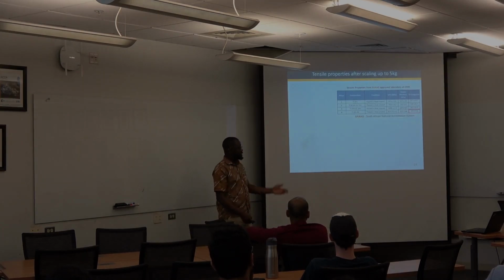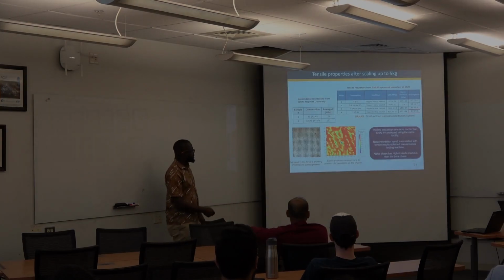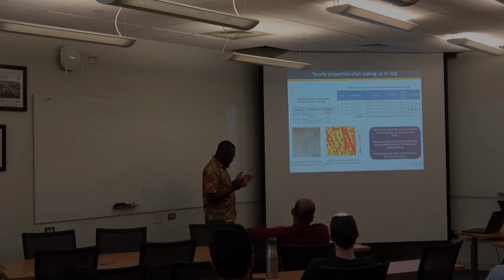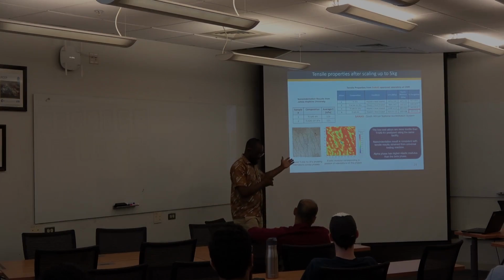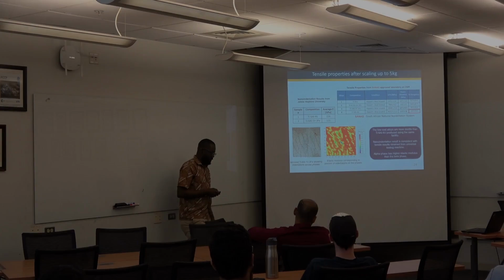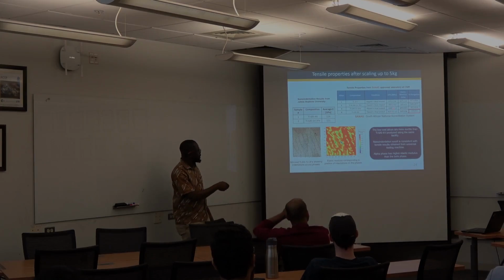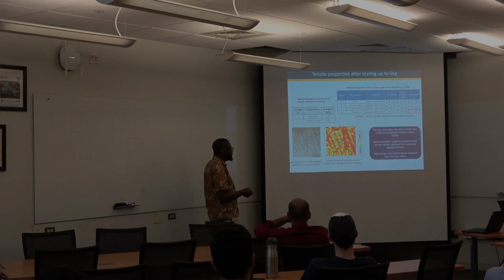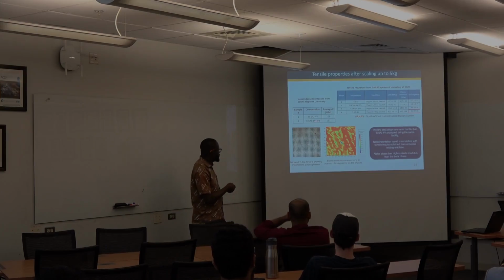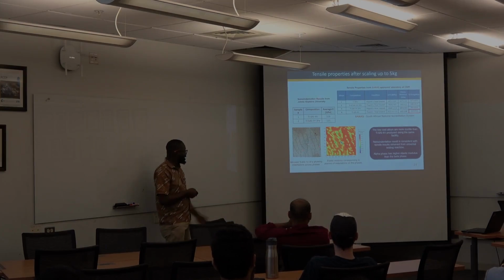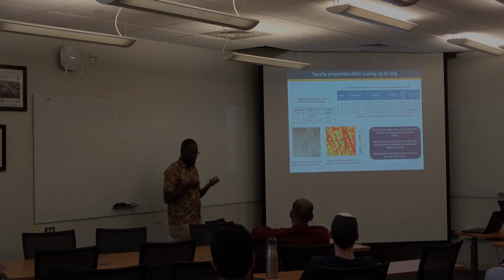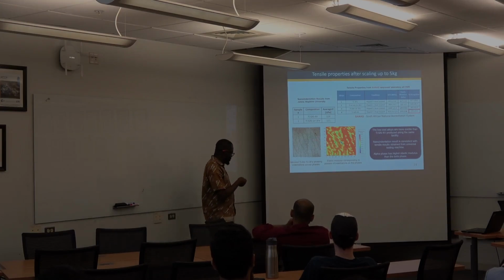So we just didn't stop at that. We tried to look at the tensile properties. So this time around, we produced all the alloys using that facility that I showed you, and of course, it's not the standard way of producing titanium. But of course, they were all produced under the same conditions, so it's easy to compare all of them. And you can see in terms of elongation, TSS4 seems to suffer. And again, we sent some of these samples to Johns Hopkins. We got some results. And sometimes that's where collaborations, the record didn't get result on time. But we were able to confirm from their experiment what we did at bulk scale.